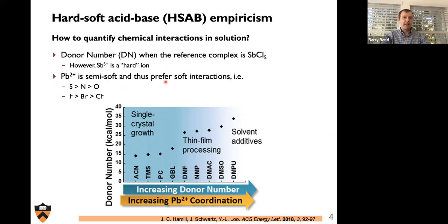And it's expected that lead will prefer soft interactions, meaning things like sulfur will be preferable over nitrogen, preferable over oxygen. And yet most of our solvents tend to be oxygen-rich solvents. And also preferred will likely be softer halide species like iodide over bromide over chloride.